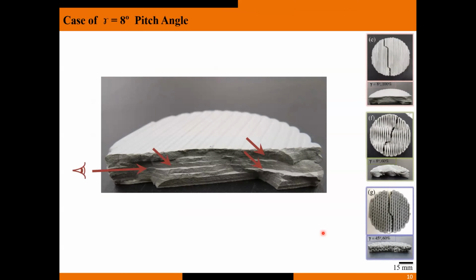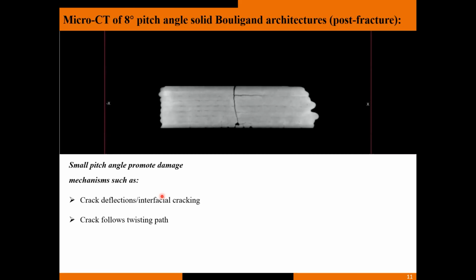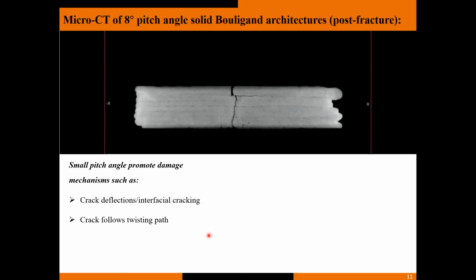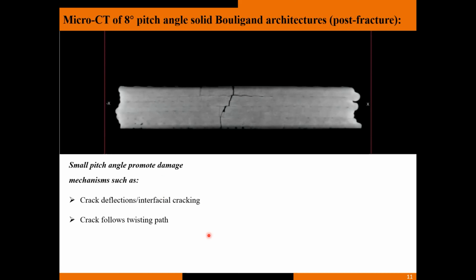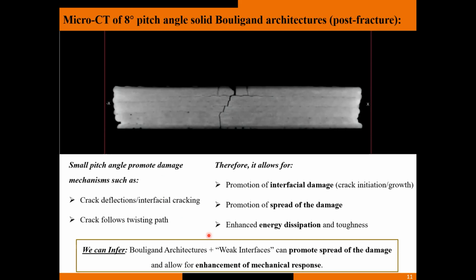So if you look at this structure, this element that has an 8-degree pitch angle, in this orientation, what you find is that there are two toughening mechanisms that contributed to improve toughness in these solid systems, one of which is crack deflection at the interface and subsequent interfacial cracking. There was also an overall crack twisting, which is challenging to trigger in a brittle system that we also observed. So together we inferred that controlling the architecture and tapping on the challenge of weakening interface, you could combine them together to improve material properties.